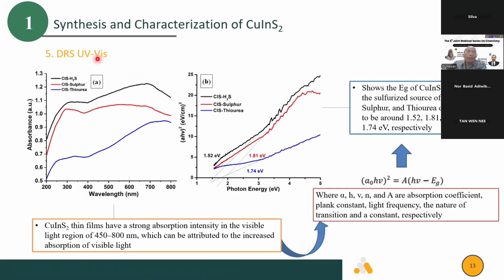So from DRS here, actually DRS is used to determine the band gap of the absorber, in this case copper indium sulfide. So we use CIS to mean copper indium sulfide. After we convert the absorbance to Tauc plot here, we can find the band gap around 1.52, 1.81, and 1.74. That is for CIS prepared from H2S, sulfur, and thiourea respectively in this case. So actually with the different sulfur sources there is a different band gap in this case.